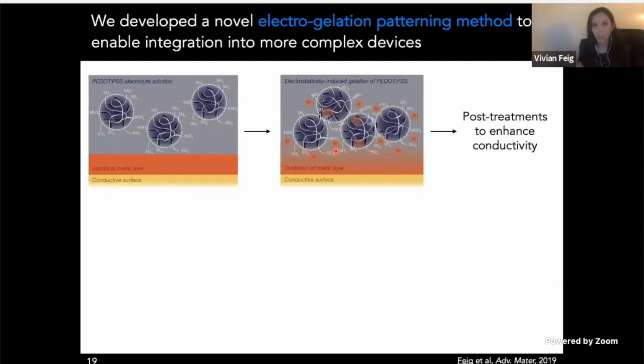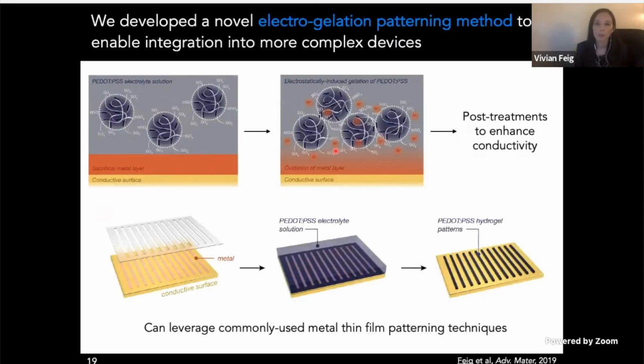And so here is where we can take advantage of those post-treatment processes to enhance conductivity, so that the main important step is just being able to shape those physical gels into your desired pattern to begin with. And with this concept, we came up with a method that we call electrogelation patterning, which has the main advantage of allowing us to leverage now commonly used metal thin film patterning techniques, including evaporation through a shadow mask. And as long as you can pattern that sacrificial metal into your desired shape, then you can use electrogelation to convert those patterns into the patterned PEDOT:PSS hydrogel.